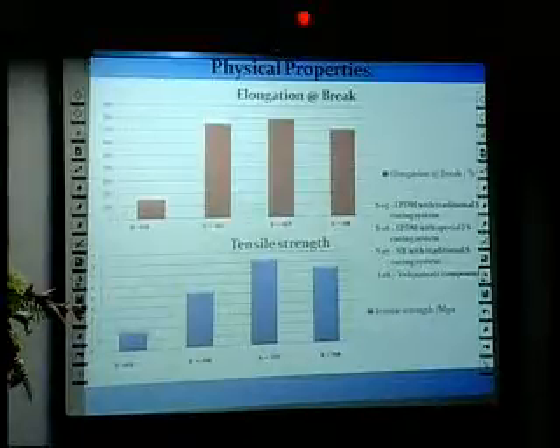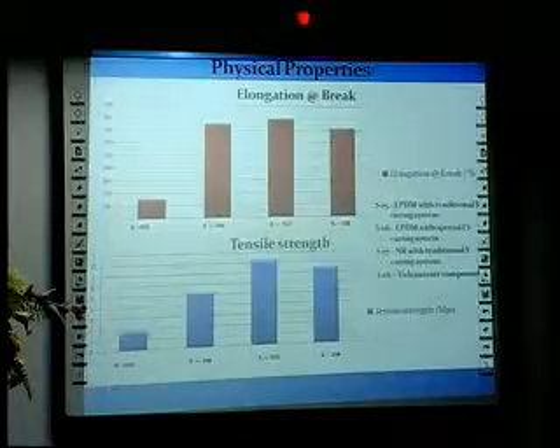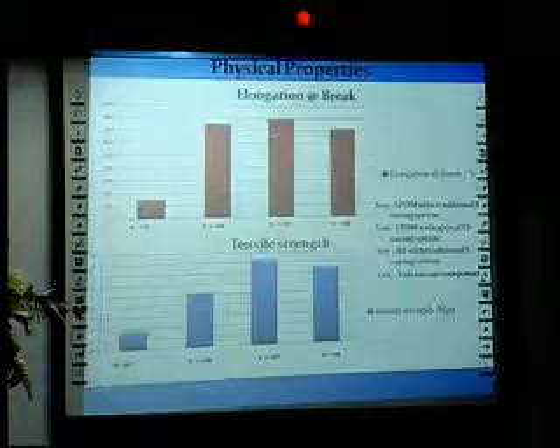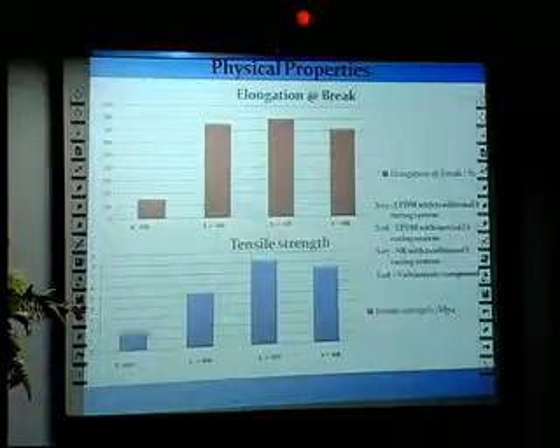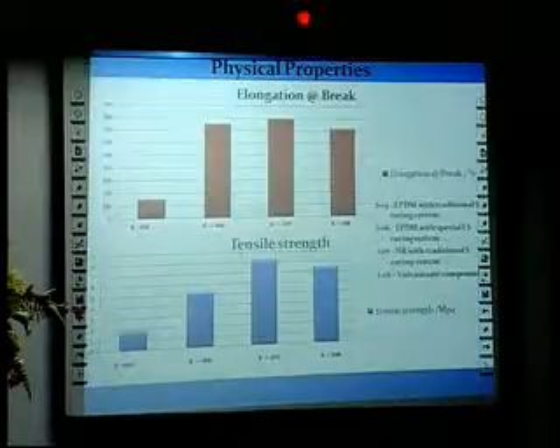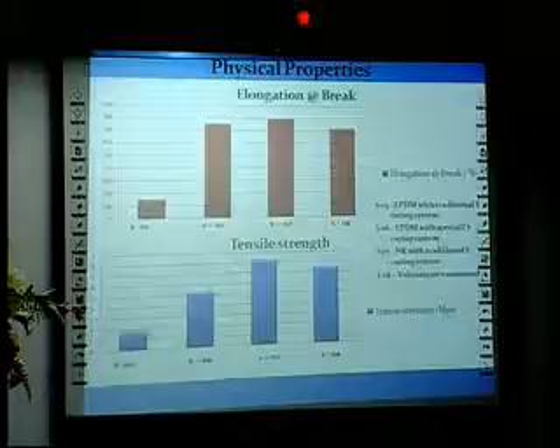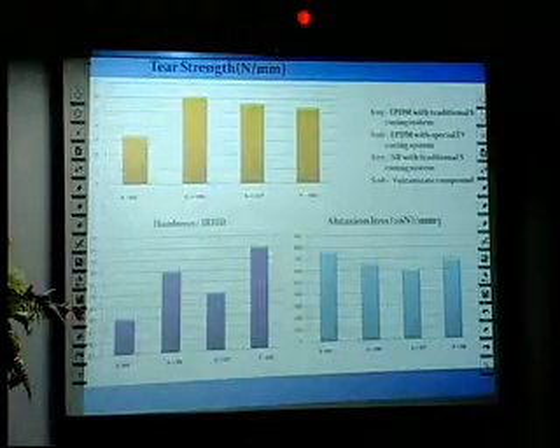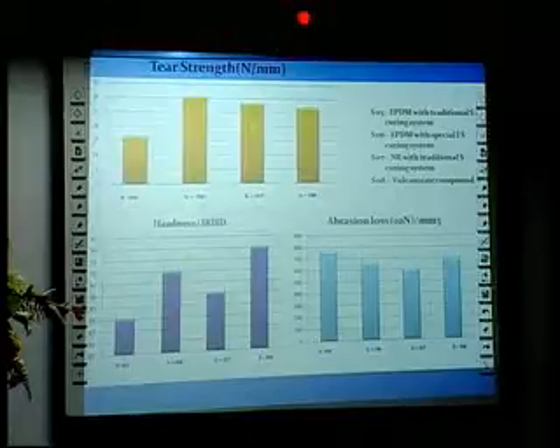It gets a very low value because of the low cross-linking. Sample 6 is the pure EPDM-based compound with the special sulfur curing system, and sample 7 is the pure natural rubber-based compound with the normal sulfur curing system, and sample 8 is the 2-layered compound with the vulcanized compound. Next, we move to the other physical properties: the tear strength, hardness, and abrasion loss.